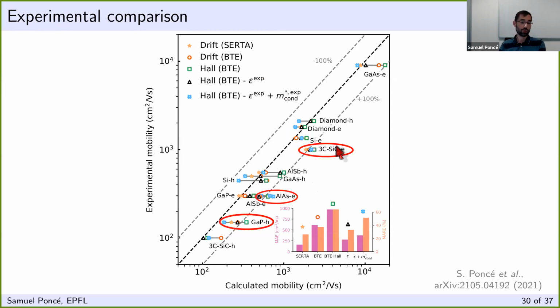Okay, just to quickly mention, for those three materials, you can see that whatever fully ab initio method I'm using, or even with rescaling, I'm always overestimating the calculated mobility quite a lot with respect to experiment. This could be an indication that experimentally it's possible to increase the mobility a bit in those compounds. I should also say that the experiments that I was able to find are quite old, maybe from the 50s, the 60s. So it's possible that if more recent experiments were done, they might increase the mobility a bit.